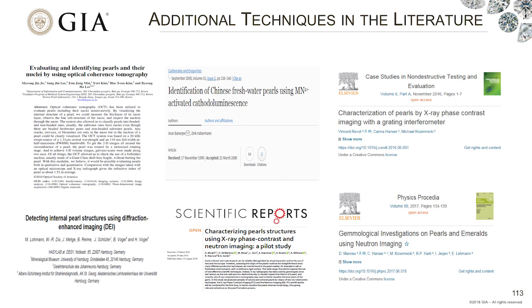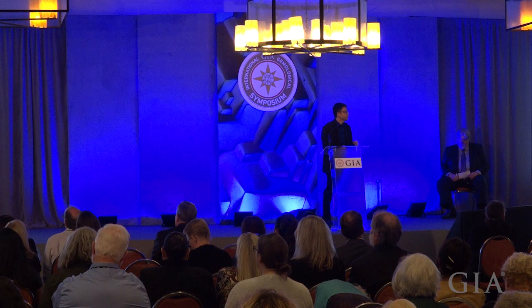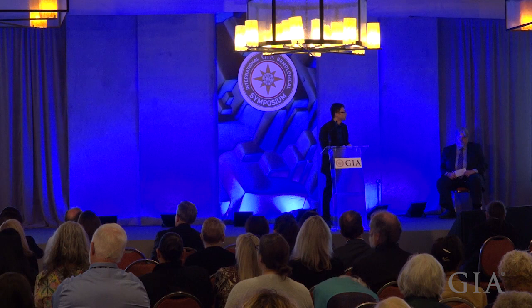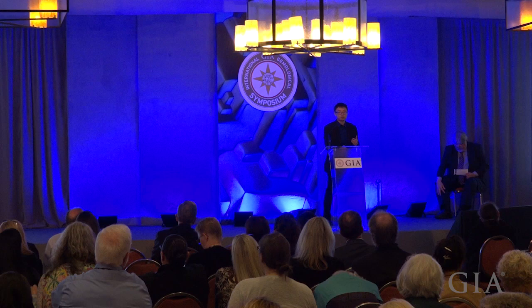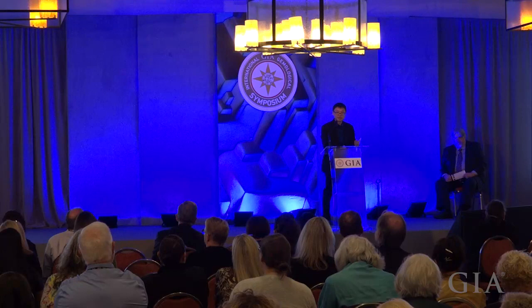Finally, there are a number of techniques mentioned in the literature which I don't have time to talk about today. Many of these techniques use alternative imaging systems — for example, X-ray phase contrast, neutron imaging, and optical coherence tomography. These techniques can give you interesting and complementary information about the internal structure of the pearls, though they also have their own limitations. In my opinion, X-ray radiography and CT technique is still the most useful technique for looking at the internal structure of the pearls. In GIA, we are going to continue to investigate different techniques to help with identification and complement existing techniques.